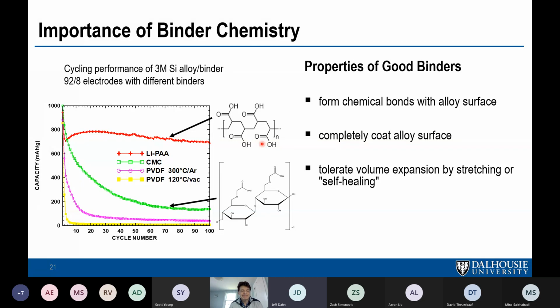That's very humorous, but when you mean carbonize, what do you really believe is happening? Do you believe you're actually getting a conducting network of carbon? Is there that much reactive elements in those polymers, that much oxygen to take away and really leave that much carbon behind? The first lithiation of polyimide corresponds to exactly the capacity you would expect for forming Li2O, Li3N, and lithiated disordered carbon. And then the voltage curve of the polymer that's left afterwards looks exactly like disordered carbon.